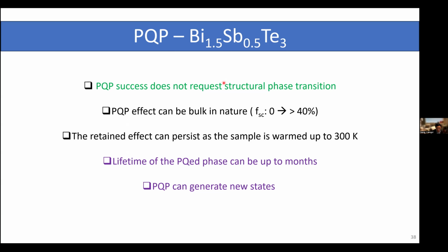It could warm up to room temperature and cool back, the TC still persists, and also the lifetime. For the BST, it's extraordinarily long. This one is so far the only example that we recovered from the DAC and kept stable at room temperature condition for a few months. And then we measured again, the superconductivity is still there. So lastly, as I pointed out, PQP can also generate new states. That's all we learned from the BST, and that's been one of our favorite experiments on PQP.